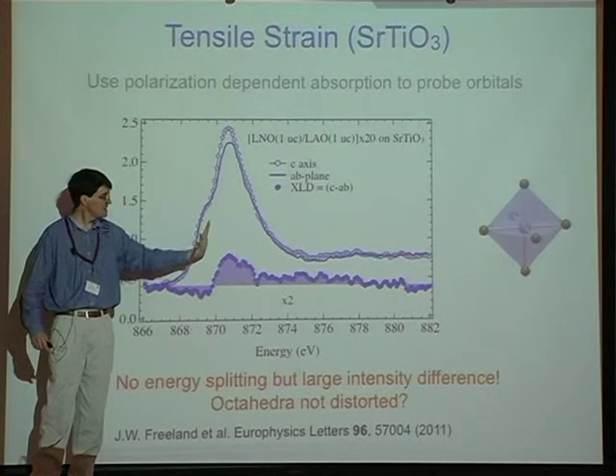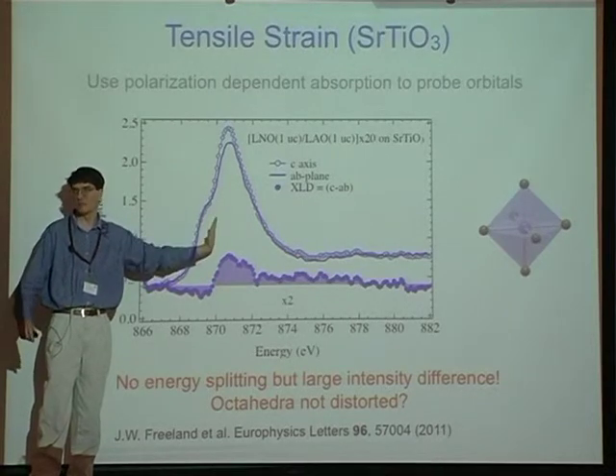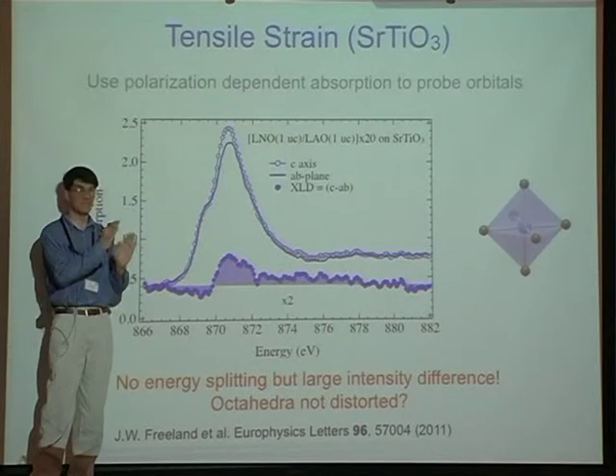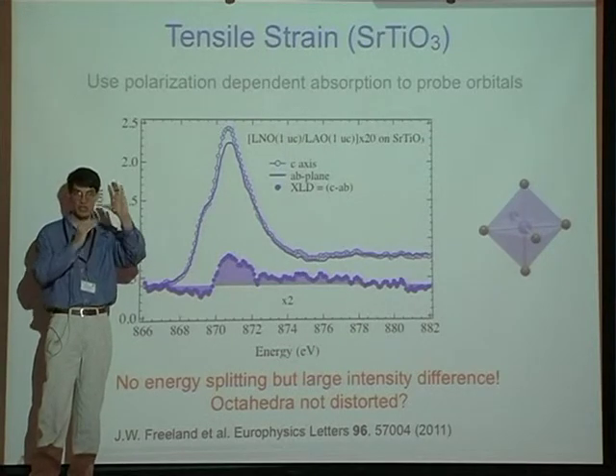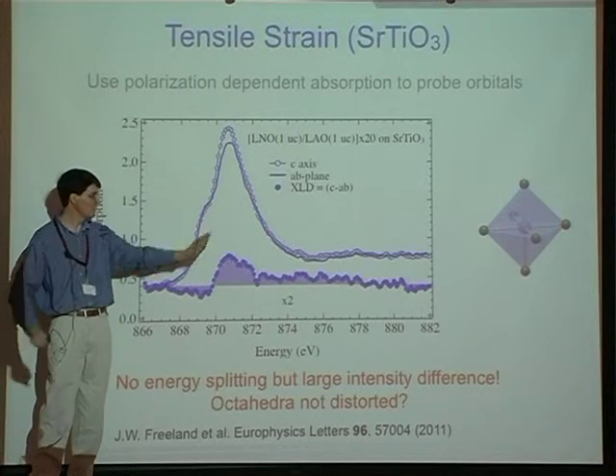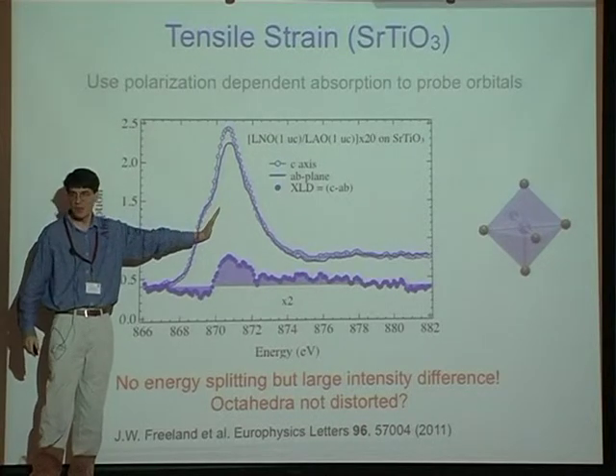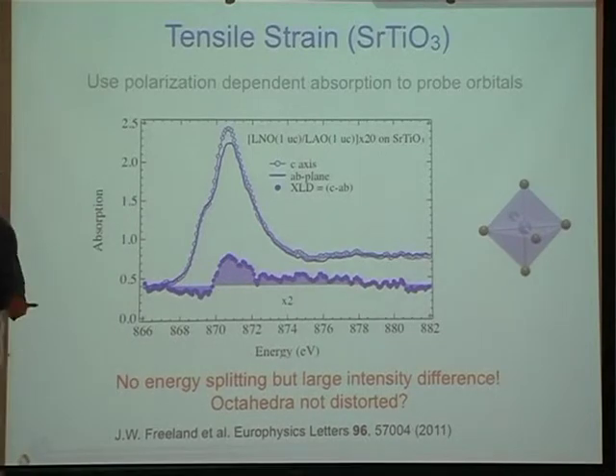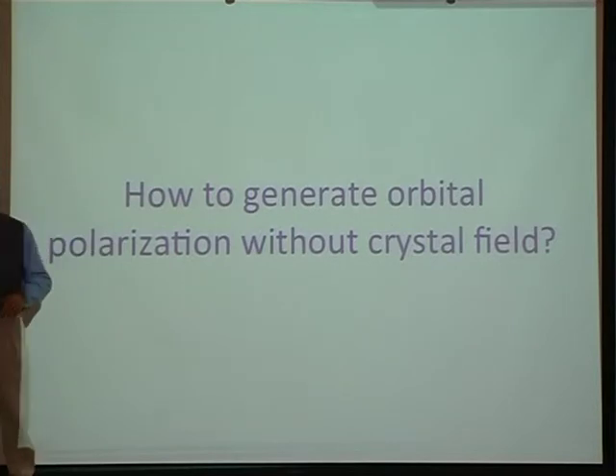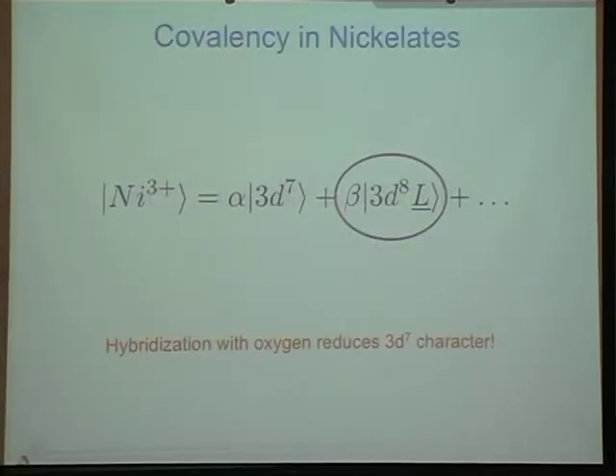But I'm also seeing that these peak positions are in exactly the same place, which they weren't in the case of neodymium nickelate. They were actually shifted because I was changing the bond length, which changes the energy of those levels. So this is a very strange problem because I have orbital polarization, but it seems like I do not have any change in crystal field. So the question is, how does this occur? It occurs because these materials are highly covalent. So this is another ingredient of nickelates that makes them both interesting and frustrating. So that the material is not really 3d7, it's actually really 3d8 with a hole on oxygen.